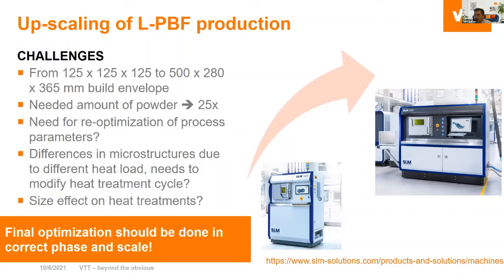And then it also has a connection to the post-treatment. So for example, in the bigger machines, the heat load of those components can be higher. That affects the as-built microstructure, and that in turn also affects the heat treatment. So in the worst case, of course, we have to make a re-optimization of this heat treatment cycle. And then when the size of these components gets bigger, that probably also has a connection to the need for different types of heat treatments.